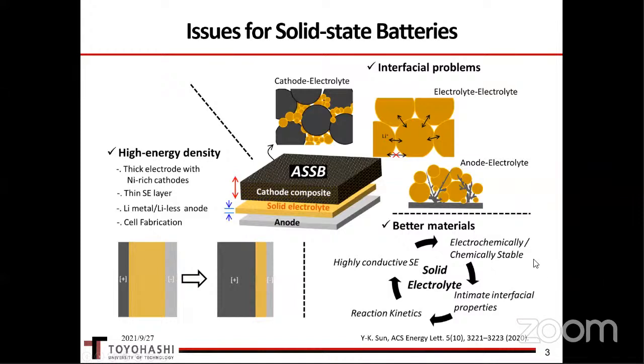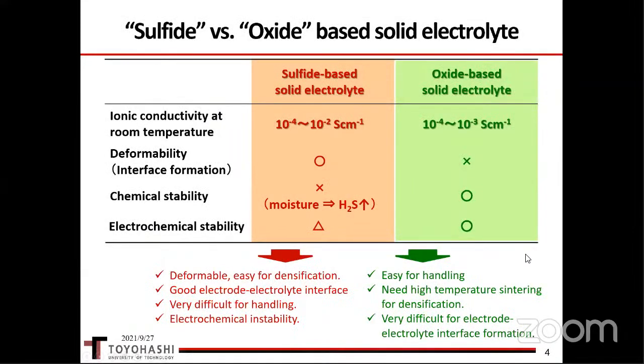Today, we have many types of ceramic sodium-ion conductors, such as sulfides, oxides, and halides. This table is a summary comparing the properties of sulfide-based and oxide-based solid electrolytes. At first, the sulfide-based electrolyte has a higher room temperature conductivity than the oxide-based one, and the sulfide can be deformed more easily compared to oxide, which is suitable for intimate contact with both cathode and anode active materials. However, the sulfide is generally very reactive with air and moisture, and its handling is very difficult. Of course, there are also some electrochemical instability issues.